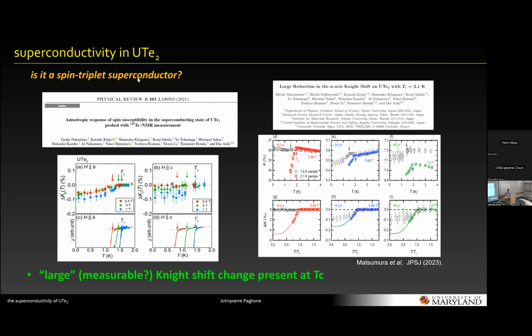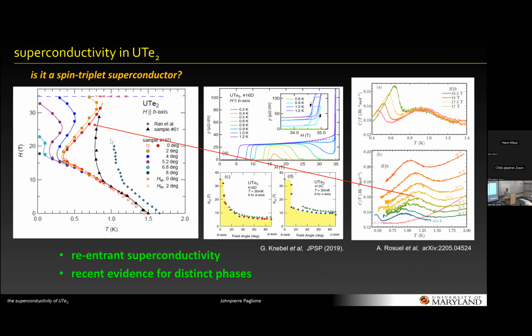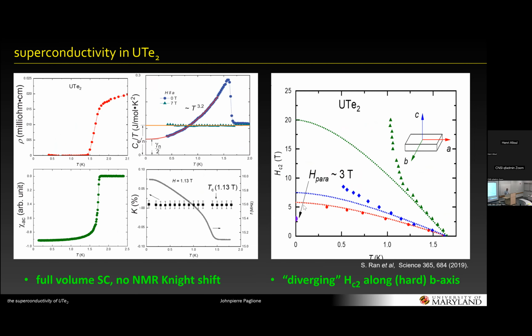Okay, so is it a spin triplet superconductor? For sure, or for real? That's the realistic question. So of course, the first argument is just that the upper critical field, in all directions, in fact, exceeds the Pauli limit. So that's a standard argument that Pauli limiting of the singlet Cooper pair is not playing a role here. So even in the A-axis direction, where the upper critical field is between 5 and 10 Tesla, the Pauli limit is still half of that, so it's already exceeded there.